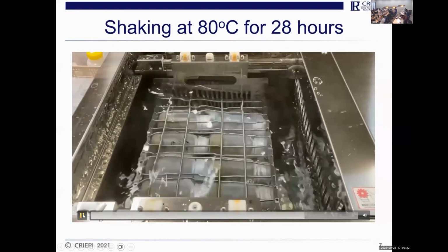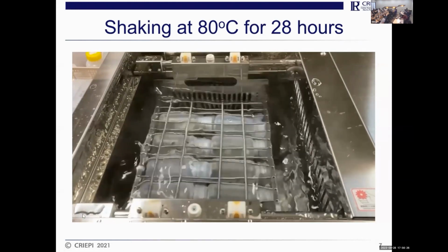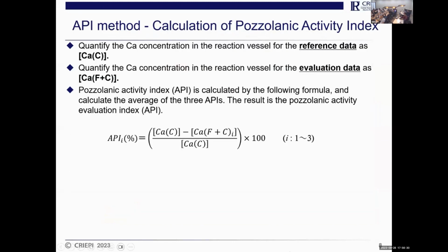We shake it in 80 centigrade hot water for 28 hours. After that, we get the data for the difference. We must obtain the concentration of calcium in the reference data, meaning that obtained from the OPC system. And secondly, we must get evaluation data from the cement and fly ash mix system, which is F plus C. And after that, we calculate API very simply, like this.